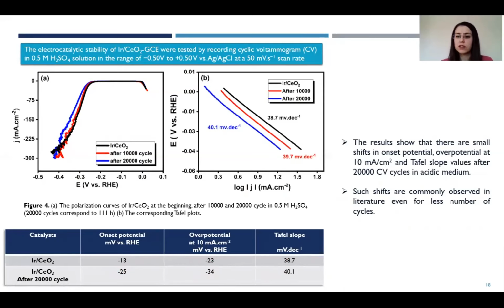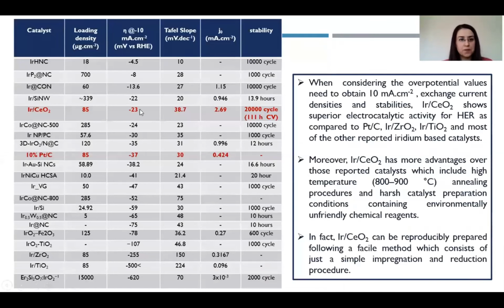Such shifts are commonly observed in literature even for fewer cycles. When considering the overpotential, Tafel slopes, exchange current densities, and also stabilities, iridium ceria shows superior electrocatalytic activity for the hydrogen evolution reaction as compared to the commercial platinum carbon and iridium zirconia, iridium titania, and the other reported iridium-based catalysts. Moreover, iridium ceria has more advantages over those reported catalysts, which include high temperature annealing procedures and harsh catalyst preparation conditions containing environmentally unfriendly chemical reagents.